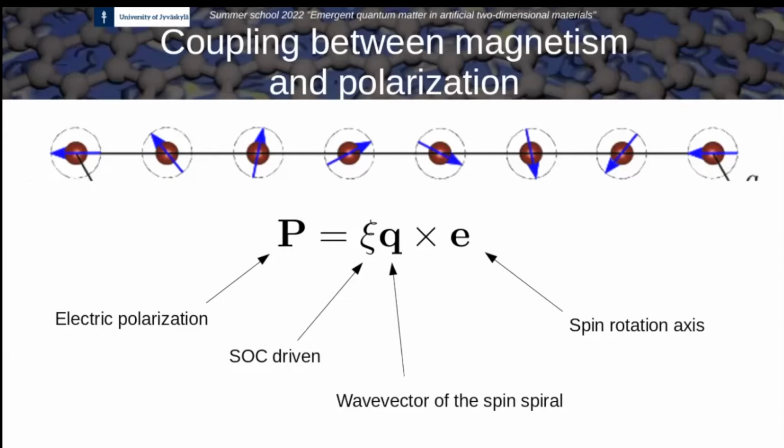That's a very good question. I would say that in that case, it may be challenging to make it work, because this spin orbit coupling is actually internal in the atom. So it's the intrinsic spin orbit coupling within the atom, and not so much, let's say, some Rashba spin orbit coupling that you apply externally. Of course, Rashba spin orbit coupling is a consequence of the internal spin orbit coupling times hopping. But when you proximitize things, you affect the Rashba spin orbit coupling, but not the internal one of each element. And this parameter here depends on the internal one.